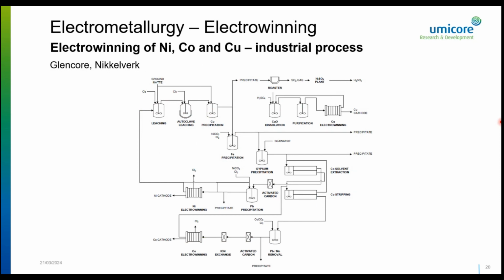To give you an idea about how this is incorporated in a typical process, we usually talk about flow sheets. We have a flow sheet to process a certain material to get the clean metals out. This is a well-known flow sheet used in Nikkelverk in Norway by a company called Glencore, and besides copper electrowinning they also use nickel and cobalt electrowinning. It's a complex flow sheet, but they are able to have feeds that contain all three metals, separate the metals, and separately perform the electrowinning process to produce copper cathodes, nickel cathodes, and cobalt cathodes. They separate these metals by precipitation of metal or by solvent extraction. Solvent extraction, for instance, is also applied a lot in the metallurgical industry.